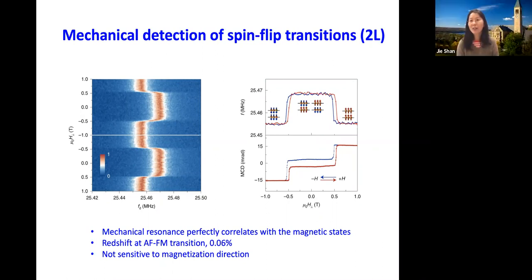Oh yes, I don't have it here, but we've done temperature dependence measurements, and so it has a Néel temperature, right? So above around that, this goes away, and of course the Q becomes a little bit worse. And this is a very good, interesting question. So this is something else we have been studying.